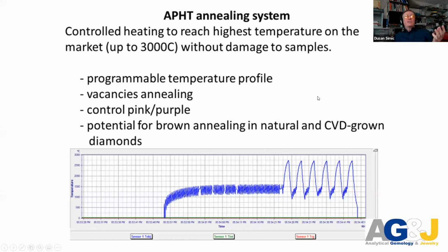APHT annealing system, with controlled heating to reach the highest temperature on the market. Of course, not 3000, because at 3000 the graphite, which is the small chamber, will start to melt without damage to the sample. How it looks. This is pulse heating. Here is a preheating in the vacuum. Nothing will happen in the diamond.